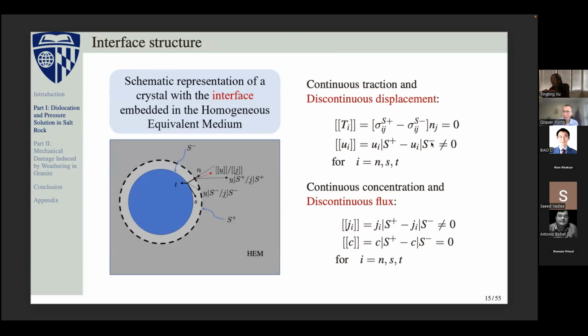With this constitutive equation, we will consider the second deformation mechanism, which is pressure solution. Here, I would say, is the innovation of this study, that we consider both the discontinuity of the displacement and also the discontinuity of the flux acting on the boundary. And we use this boundary phase or the contact phase to simulate the pressure solution deformation mechanism. So we have this jump on the displacement and on the flux about this grain contact.